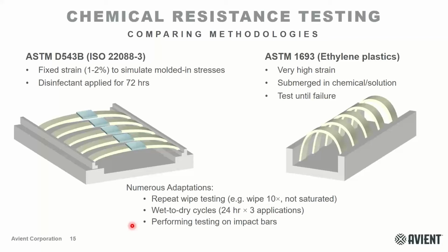You could also have wet to dry cycles where, as that disinfectant dries out, you reapply a freshly soaked gauze pad. This is the method that we tend to use. And then there are other deviations where maybe you'll test it on the impact bar instead of a tensile bar. So a lot of how you do this test depends on what you define as your critical requirements.